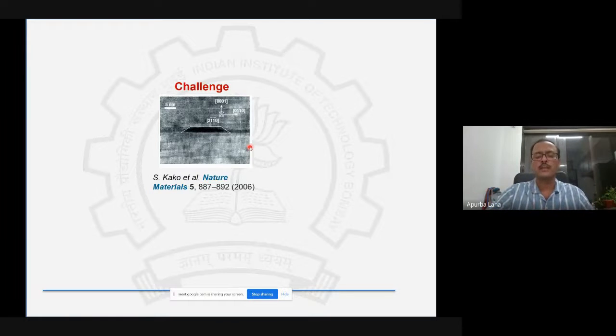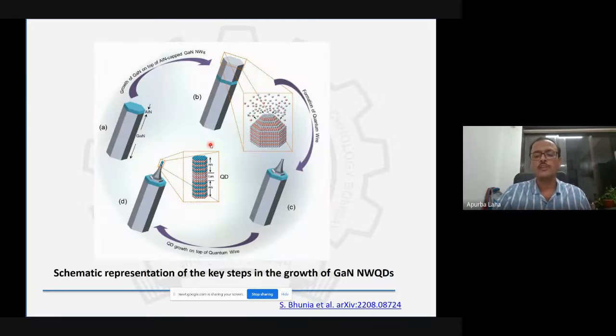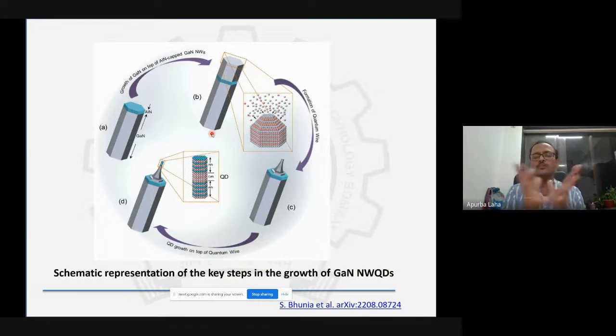But if you look at this structure, it is not typically a quantum dot. It's sort of an island structure, because the gallium nitride wets the aluminum nitride. So it's quite difficult to produce a real quantum dot. So what we adopted is that we use this nanowire as the template, and then we convert this nanowire into a quantum wire, and those quantum wires are holding a template to place those quantum dots.